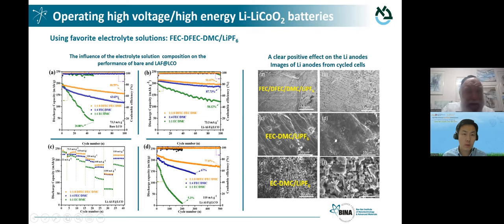And so we use fluorinated co-solvents. Using fluorinated co-solvents compared to conventional ones, we can increase the specific capacity because the fluorinated solvents affect both the negative and the positive. So we have coating on the positive, and we have also the effect of the fluorinated co-solvent, which affects the surface by a unique surface chemistry that we'll discuss. And in such a way, if you compare the orange curves here and here and here, we can see how we can stabilize the materials at a high specific capacity during hundreds of cycles. And this is also a very positive effect on the lithium side. This is well reflected by post-mortem analysis that shows that with our favorite electrolyte solutions comprising fluorinated solvents, we have smooth lithium surfaces after prolonged cycling.